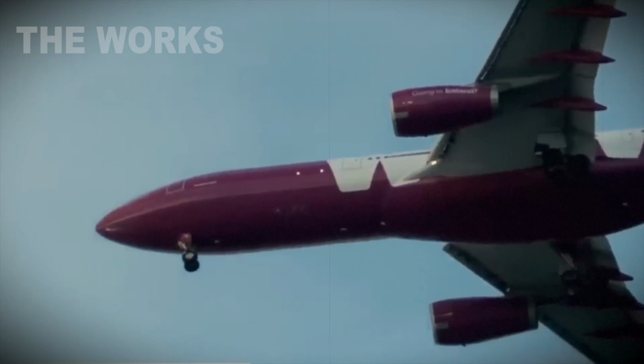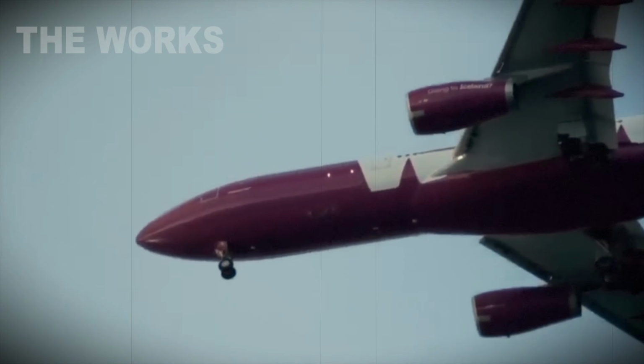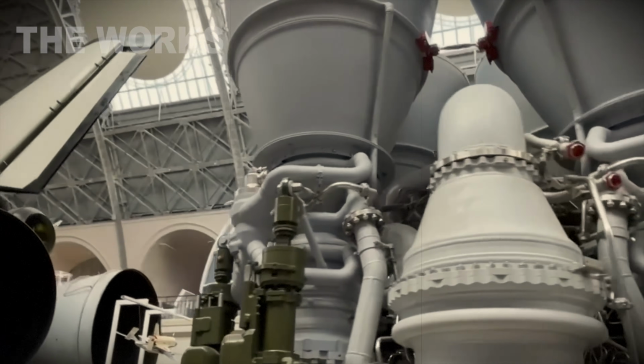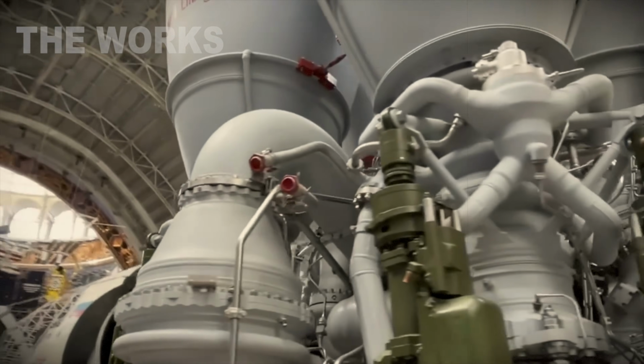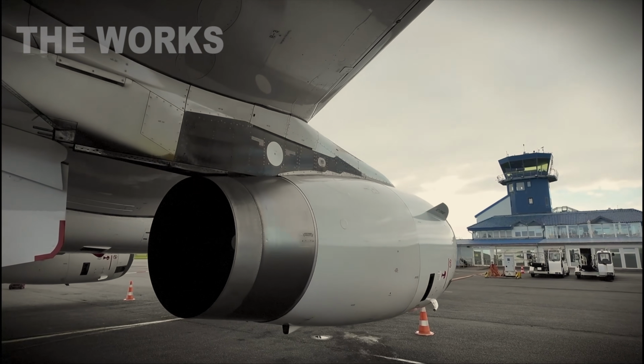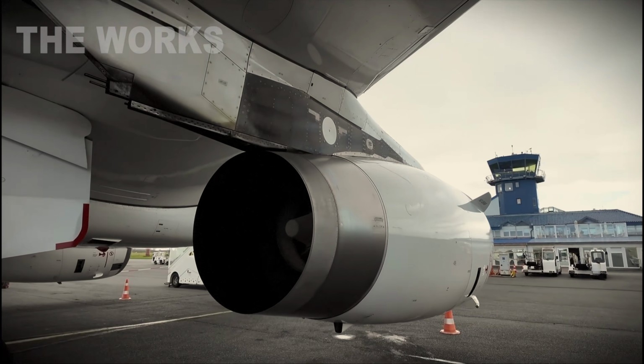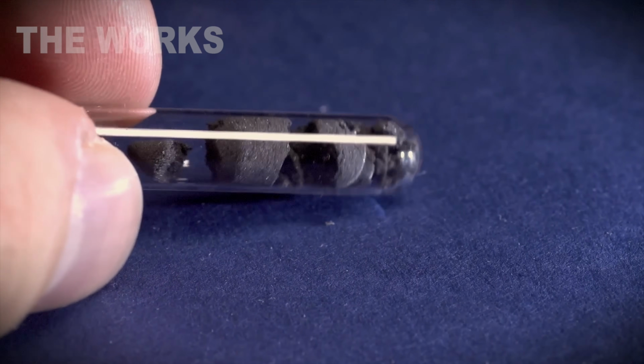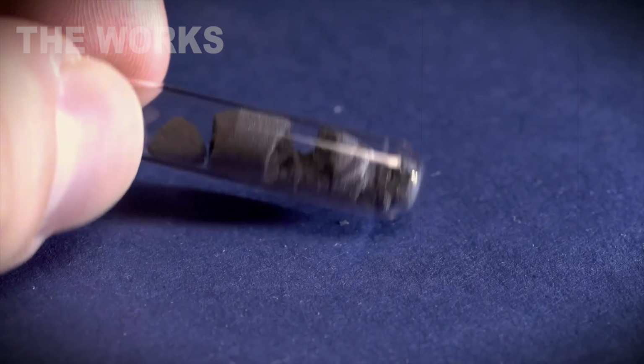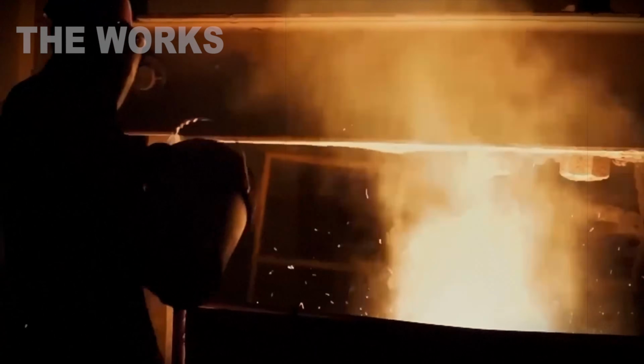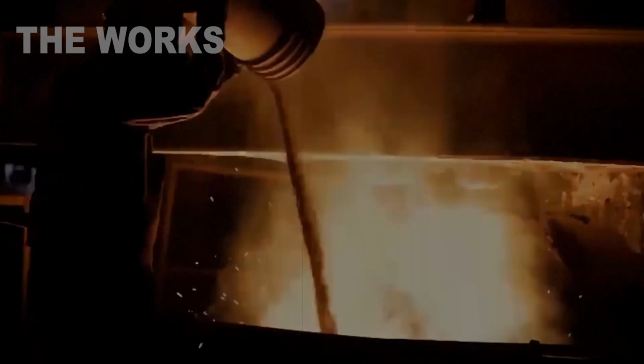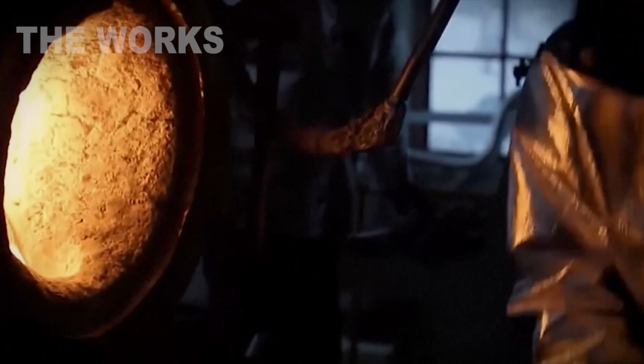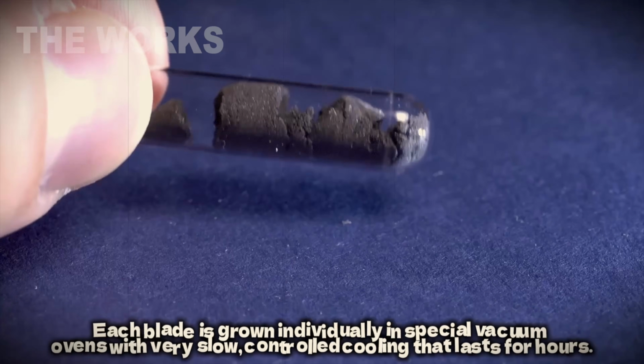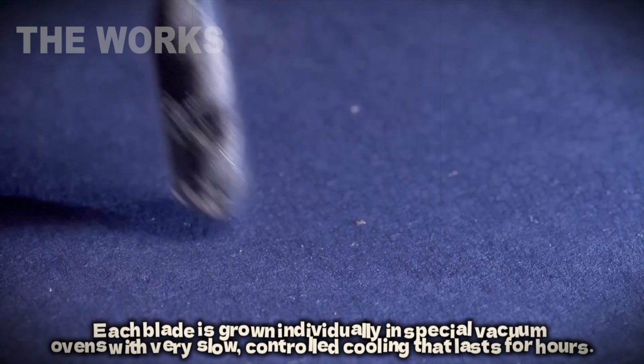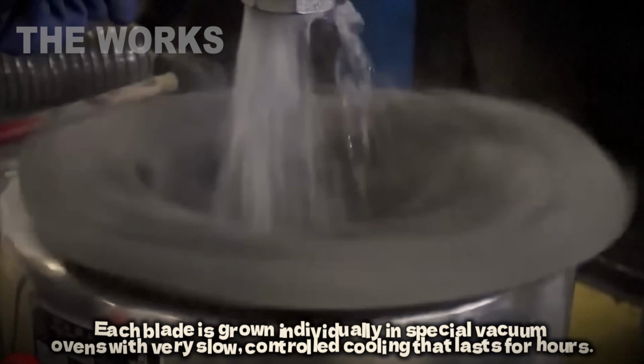Single crystal blade technology makes rhenium work smarter. Instead of a regular polycrystalline structure, each blade is grown as one massive crystal with no grain boundaries, which are weak spots at high temperatures. This lets you cut down on rhenium content while keeping performance. But the process is complex and expensive. Each blade is grown individually in specialized vacuum furnaces with extremely slow, controlled cooling that takes hours.